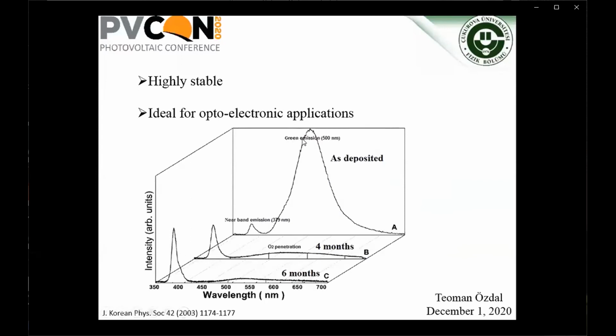Here, as deposited, we can see green emission around 500 nanometers. After 4 months, oxygen penetration makes the emission lesser, and after 6 months, the zinc oxide is optically ideal for the visible region. Near-band emission, by the way, decreases over time.